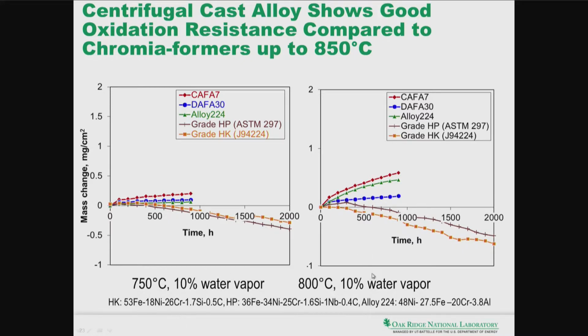On the right-hand side, you're seeing the 800 C data, where these effects are magnified. As you can tell, the DAFA 30, which is the gamma prime strengthened alloy, performs better than the other alloys, probably the best within this time scale. And the CAFA 7 and the alumina-forming nickel-based alloys keep very close track of each other. So what this already demonstrates is the potential offered by the alumina-former in terms of providing good oxidation resistance.